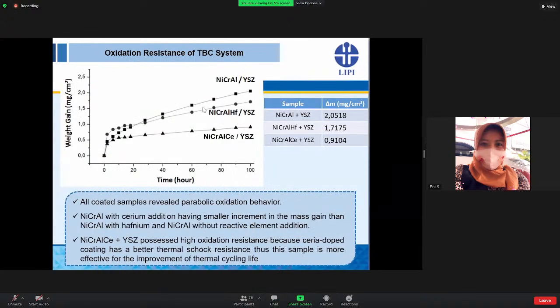This figure also shows the oxidation kinetics of the TBC, which is complete with the bond coat and the ceramic top coat. All coating samples reveal a parabolic oxidation behavior. The weight gain varied over the 100 hours, and the cerium addition has the lowest mass gain, about 0.91 milligram per centimeter square. So it verified that nickel chromium aluminum with cerium has a smaller increment in mass gain compared with the other 2 samples. Therefore, the cerium addition is more effective for improving thermal cycling life.